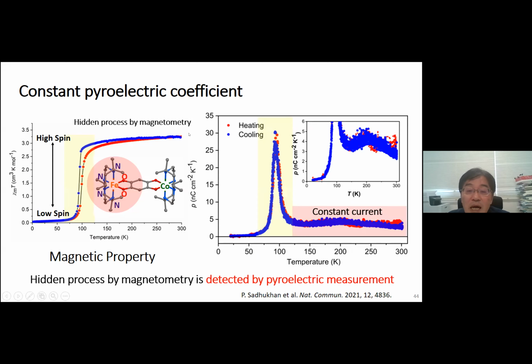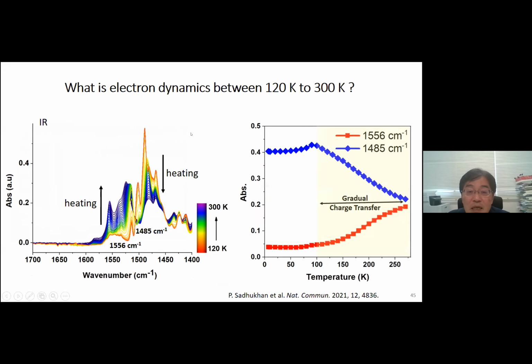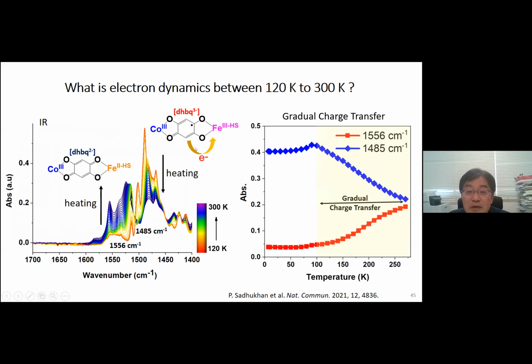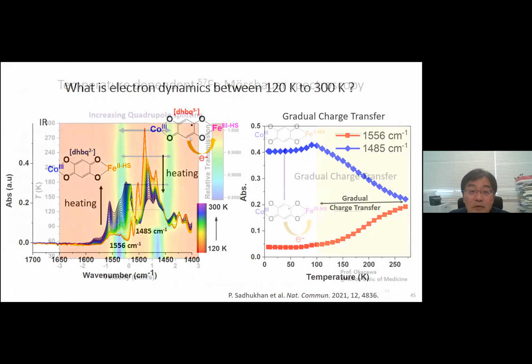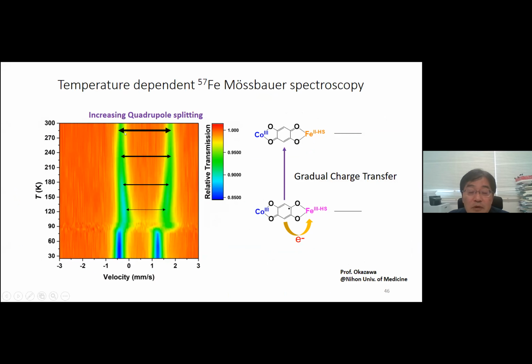So we characterized this process using IR spectroscopy above 100 Kelvin, above the spin transition temperature. This peak decreases with increasing temperature, and this peak increases with increasing temperature. This suggests electron transfer is induced above 100 Kelvin. Gradual charge transfer occurs. And this is confirmed by Mössbauer spectroscopy. Quadrupole splitting increases with increasing temperature. This means the excited iron 2 high-spin state is populated with increasing temperature. This is the origin of the pyroelectric current.